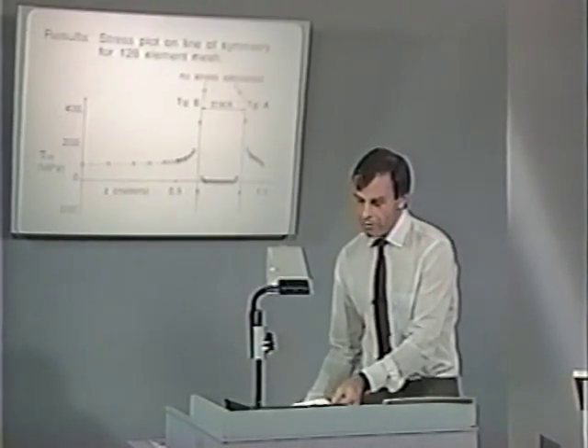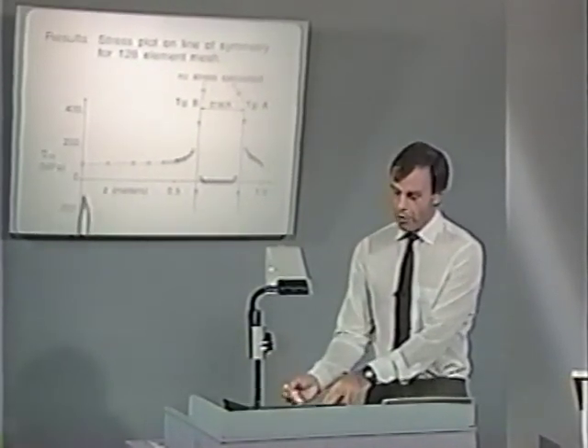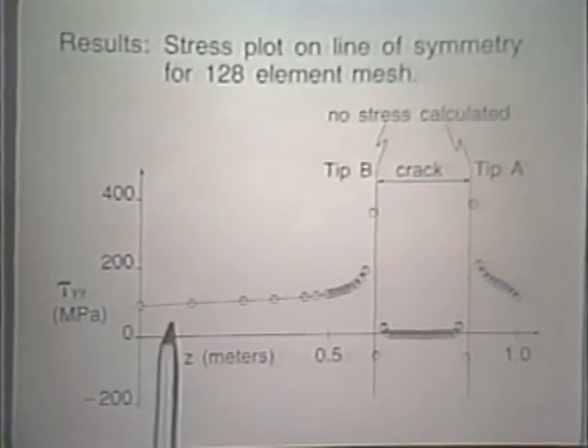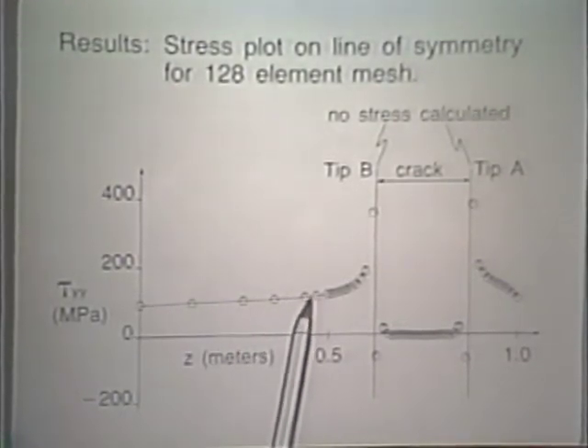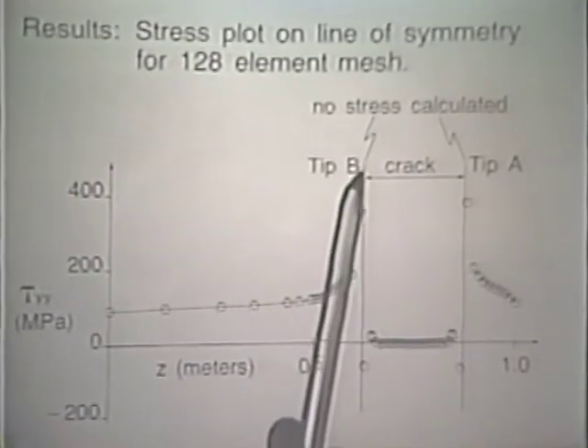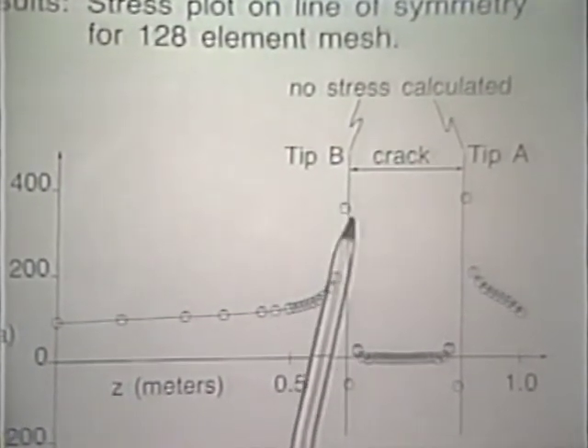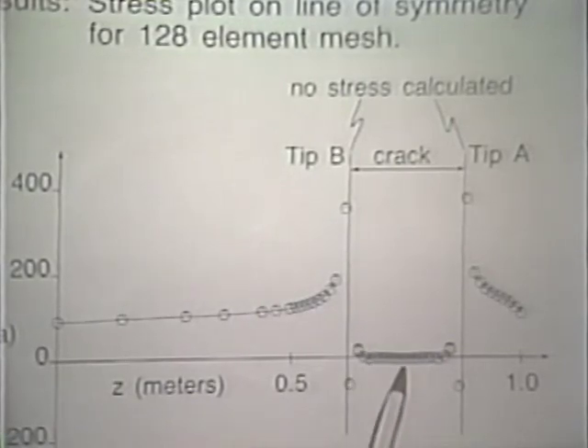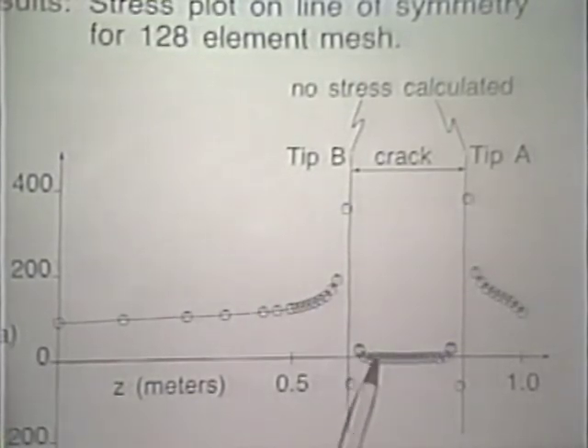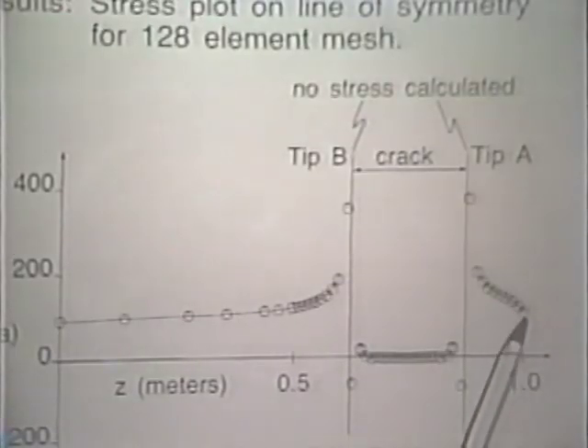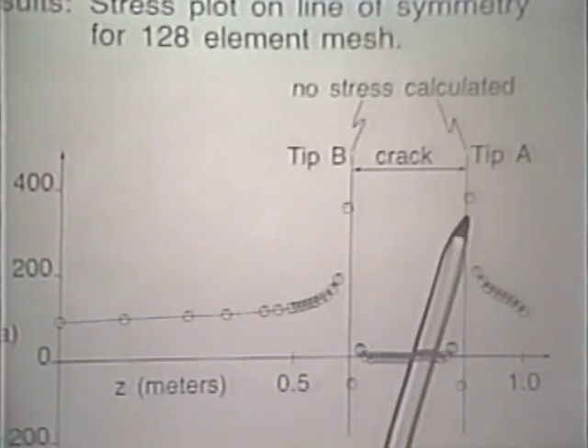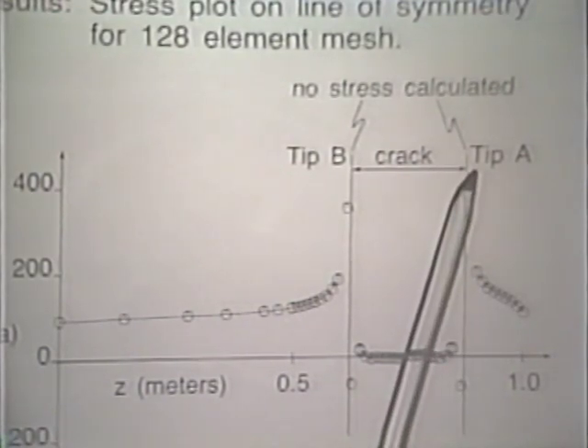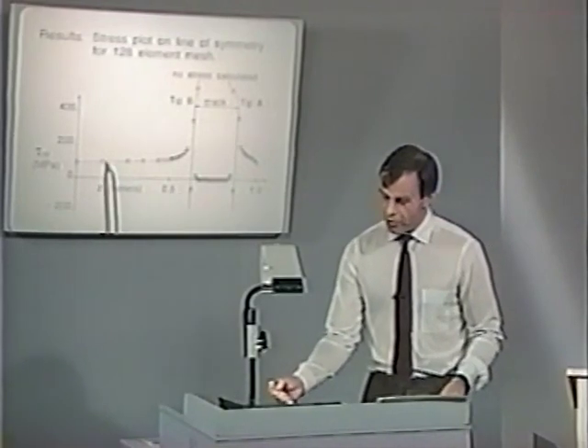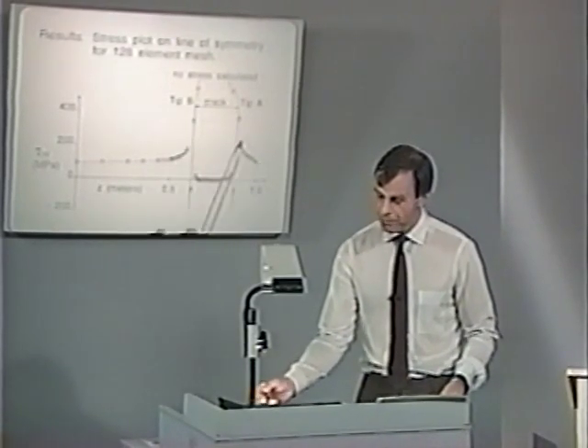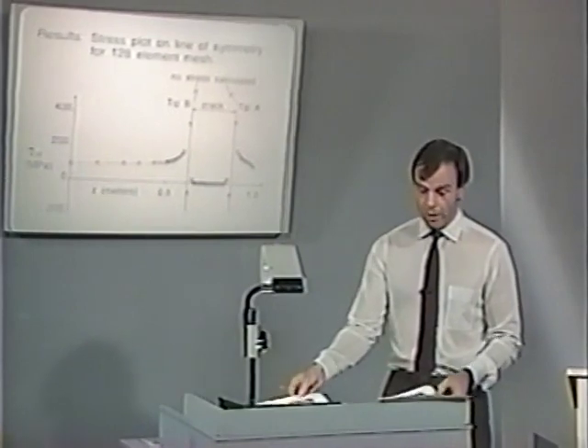Now we look here at the stresses. Stresses, tau yy, as I pointed out, as a function of z. And you can see here a stress that very rapidly grows. Then on the other side comes down to practically zero in the crack area. And on the other side, coming again now from the right here, a stress that varies very rapidly up close to tip A. We also can see here that the stress variations are nice and smooth. Of course, that indicates to us that the mesh is really a good mesh.